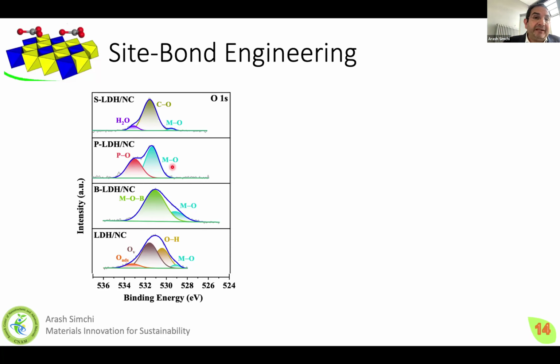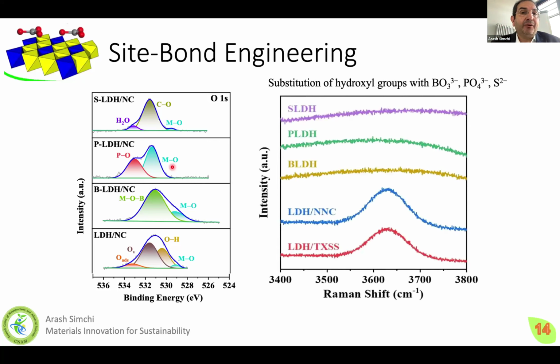What does it mean? It means that when we substitute different cations and anions in the system, we create oxygen vacancies. If this is true, then we have to see a very nice example, for example, in the Raman shift, that some of the symmetry of the crystal structure is broken, and sometimes even some peaks are removed, meaning that we have a kind of quasi-amorphous structure instead of a crystal structure. The good point about this structure is that the conductivity increases because we have a lot of oxygen vacancies and we have a disordered crystal lattice.